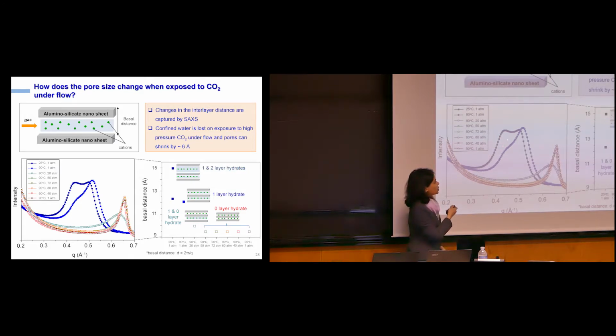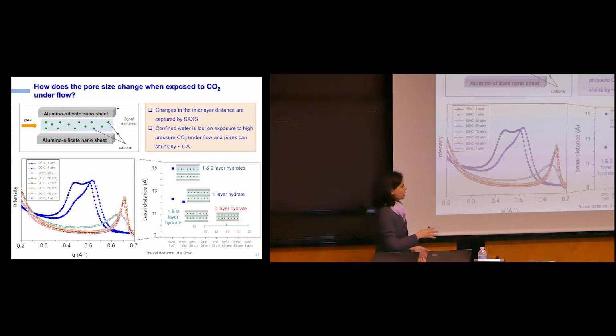As we add more CO2, we're depleting the second-layer hydrate. We have one layer. As we add more and more CO2, we're depleting this more and more to the point where there's no water left. And not only that, we're basically shrinking these materials down. So these materials that actually started out with a representative basal distance of 15 angstroms now are at about 10 angstroms. So effectively, we are shrinking them down by about 5 to 6 angstroms, if you like.